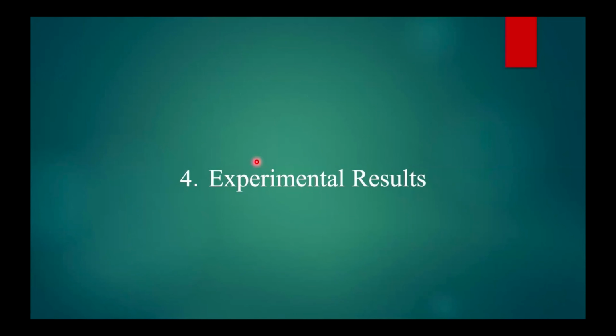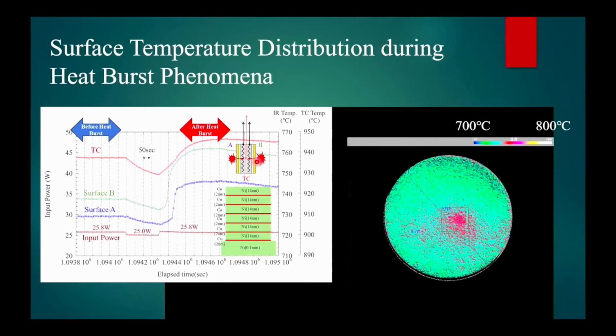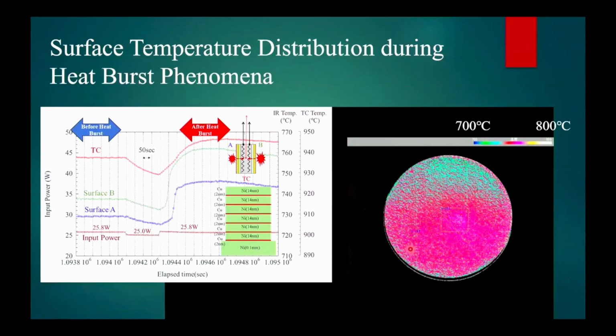Okay, and this is the experimental result. This is a movie of the surface temperature distribution during heat bursts. At the lower temperature, 700 degrees centigrade, and higher here, we can see the heat burst phenomena like this.